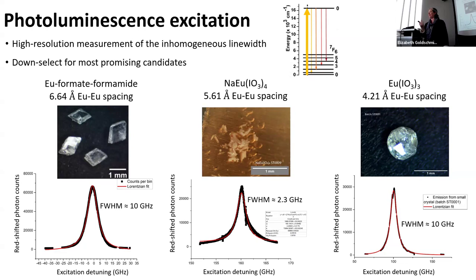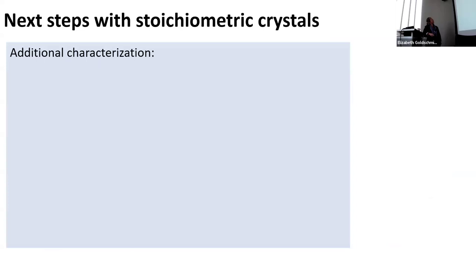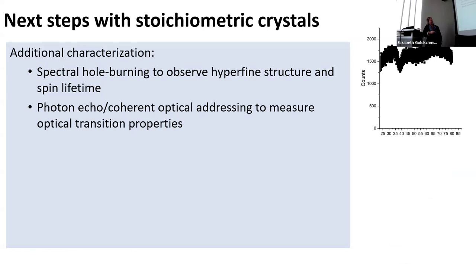We've got a long list of things to do now that we have this photoluminescence excitation working. So, spectral hole burning. This is hot off the presses. We burned a spectral hole in one of those crystals. So come in with a laser, it should optically pump atoms into other spin states. And thus we should get fewer atoms at the place where the laser was if you come back in with another laser and scan it across. And that's what we're seeing here, that we can burn a spectral hole.